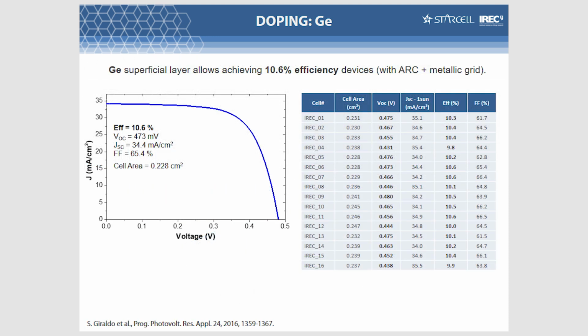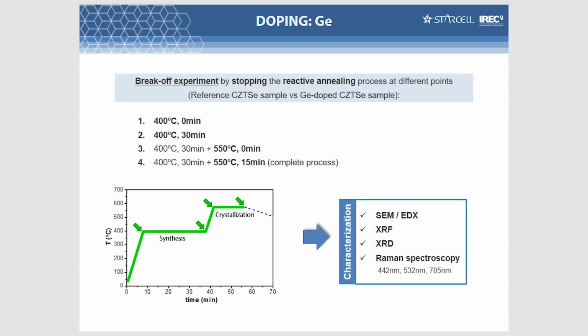At that time, collaborating with IMRA in France, we obtained almost 11% efficiency, and that can be very reproducible. Once we start to introduce germanium in our system, reproducibility becomes much higher. Then we need to understand what happened with germanium, what is the other effect, because we cannot explain this efficiency improvement only with these huge grains, and what we do is a break-off experiment.